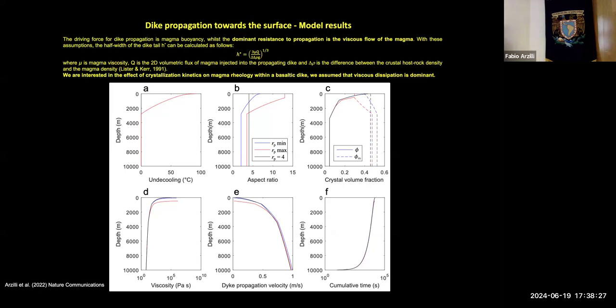So we have the red line, which is the maximum, the blue line is the minimum, and the black one is just constant aspect ratio. So what we see during ascent, here we simulated an ascent from 10 kilometers to the surface, and the question was how crystallization will affect magma ascent within the conduit. So we see that the aspect ratio for the black is constant during ascent. For the red one, when crystallization is promoted, it will increase really fast because the approach to equilibrium is really fast. For the blue line, we have an approach to equilibrium that is slower.